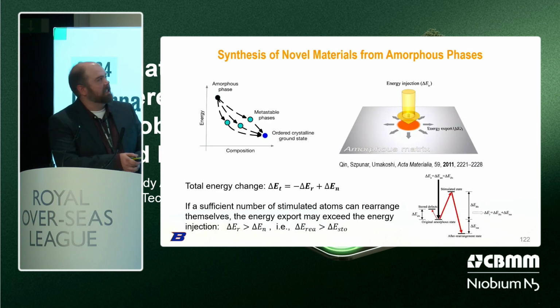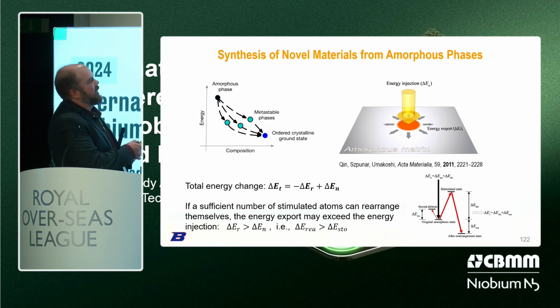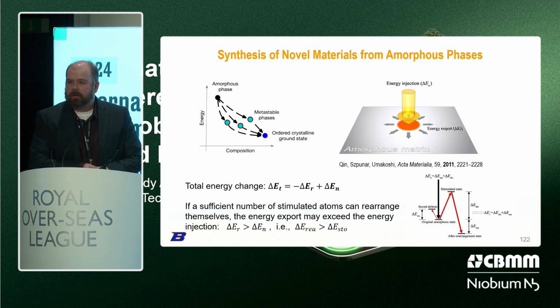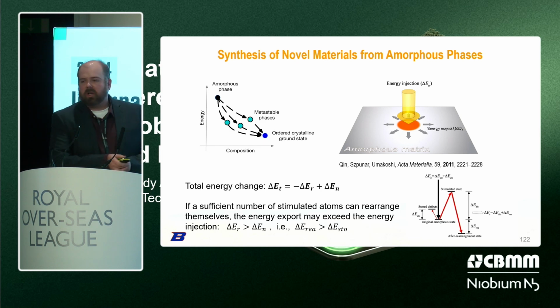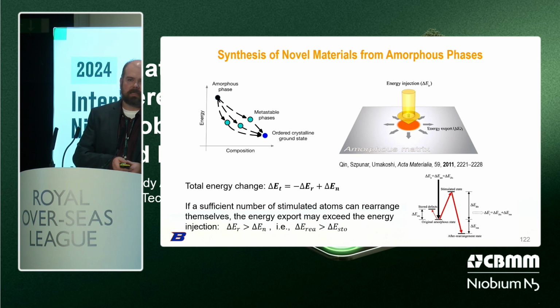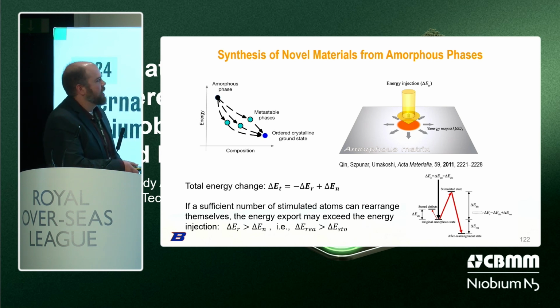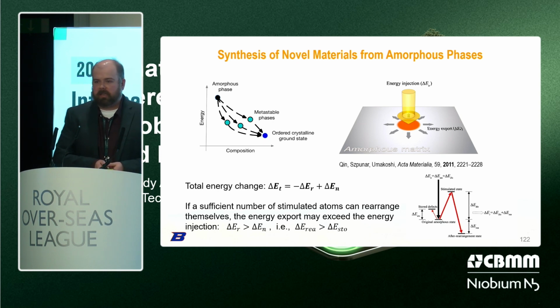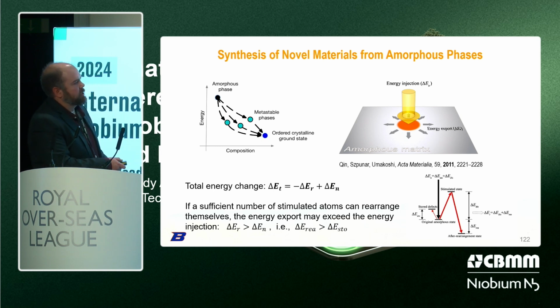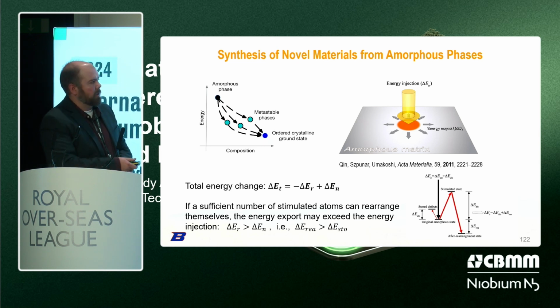So, highlighting this a little bit, you start at this upper threshold, and a lot of times we miss this gap, right? There are metastable phases that exist that aren't quite approachable through the normal techniques we associate with creating different crystalline structures. What's important is that when we inject energy into a material, it's going to have an amount of defect energy associated with it, and also a stimulated state. Those combinations end up in a rearrangement of the material that is optimal and creates a total rearranged energy, which is higher than the stoichiometric, or the stored.